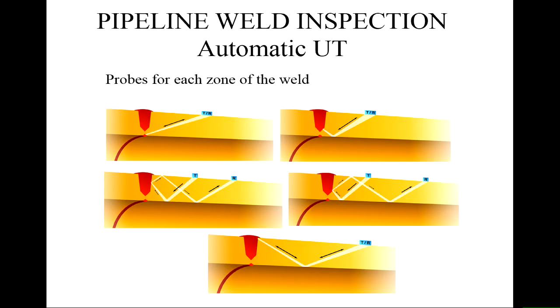So how do we do that? Well, we have really a different detector for each part of the weld. So the transducer and the receiver have an angle, and the sound wave can bounce off the root pass and come back down. Slightly closer, slightly different angle, we get a bounce of that sound wave off the back of the pipe and then up to a defect perhaps in the hot pass. And then we can have separate transducers and receivers where the bounce pattern for the sound waves can be from the different passes up through the system. And then you might have an even further spaced transducer receiver which has a bounce and then comes up from the top.